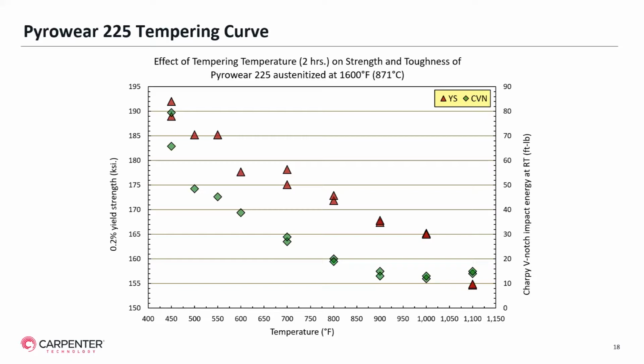For all of these data, what we've done is we've taken water-quenched Pyrowear 225 that had been austenitized at 1600 Fahrenheit, water-quenched, and we tempered at the various temperatures along the x-axis. As you can see on the left-hand side, we get the highest strength and the highest toughness tempering at 450 degrees Fahrenheit. And as we increase the tempering temperature, we see a monotonic decline in both the yield strength as well as the Charpy V-notch impact energy. That's why I said in an earlier slide that this alloy is designed for temperatures of operation that are at 600 degrees Fahrenheit or less.